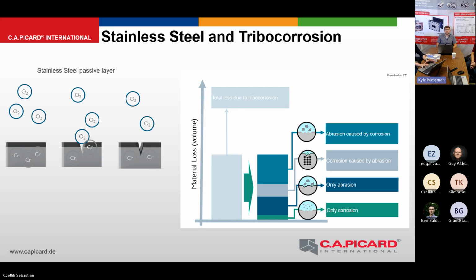That means the mix of abrasion and corrosion. And as you can see, here's the total loss of material in this light blue. And this consists of 4 parts. So we have the part which is only caused by corrosion, so material is vanished because of corrosive attack. And we have the part which is only abrasion, and that we could measure relatively easily, and we can do tests which simulate this, so we can forecast it.